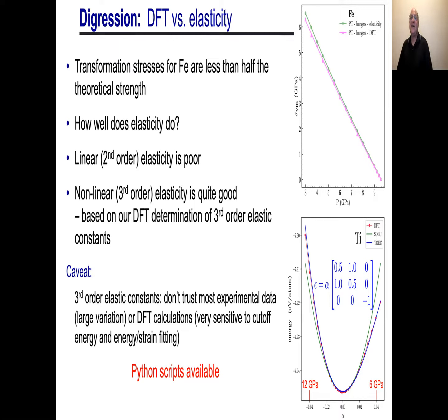And the reason is, if you look at the experimental data for third order elastic constants, the variation is tremendously large. And if you do DFT calculations, it's very sensitive to what your cutoff energies are. It's very sensitive to exactly how you do the fitting of the curves in order to extract the third order elastic constants. So you can do it.